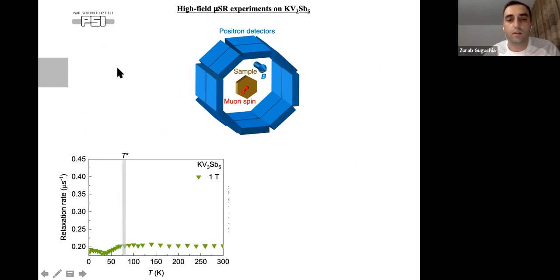So to substantiate the zero field muon measurements, we also did high field muon experiments, where the configuration is a bit different because here the muon spin is rotating around the plane, and then we apply a field along the c direction. So we collect all the positrons by all these 16 different positron detectors.